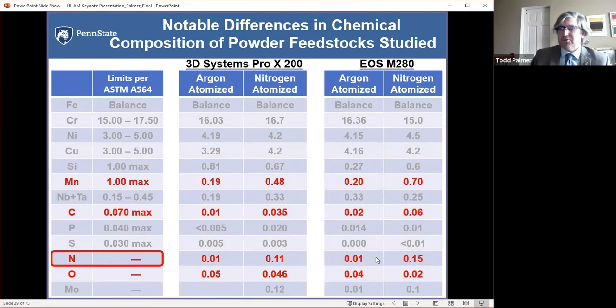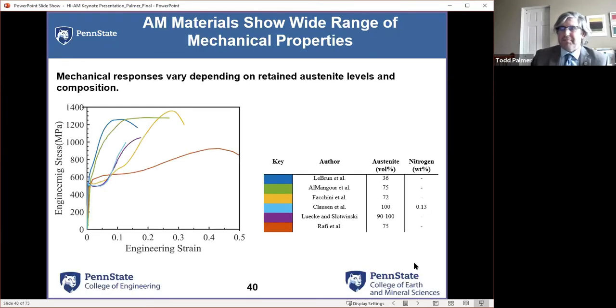So we see almost an order of magnitude difference in nitrogen between an argon atomized and a nitrogen atomized PH grade powder. Now, these mechanical responses are taken from the literature. If you're a designer, there is no way that you can start designing for PH grade stainless steels or 17-4 (17 chrome 4 nickel) in this case, with such a wide disparity in the as deposited levels.